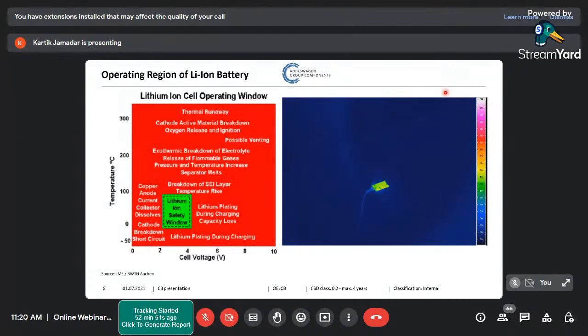So basically, as I told you, everything in life comes with some compromise, and that is true here in lithium-ion cell technology also. You have a very high energy, but that high energy is available safely only in a particular window of voltage and temperature. If you exit that window, you are in a very unsafe zone. Normally we say lithium ion cell technology works between 2 to 4 volt. I would normally say around 2.5 to 4 volt. If you exceed 4 volt, meaning you charge your battery more than 4 volt, normally we can go a maximum of 4.3 volt with our electrodes.